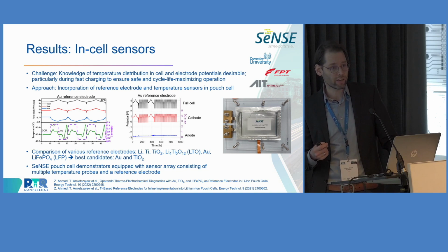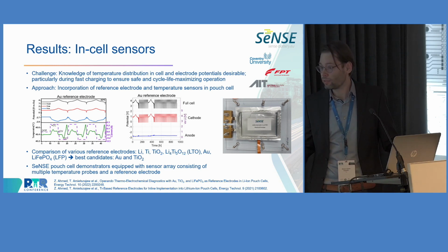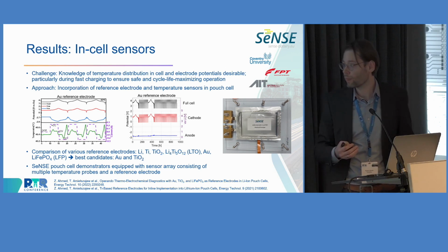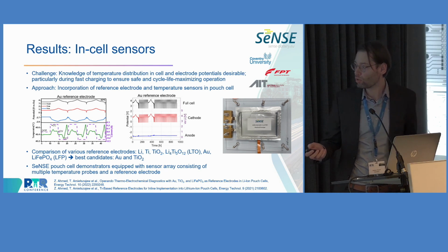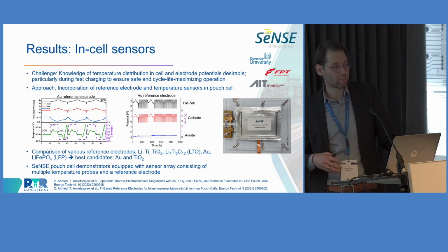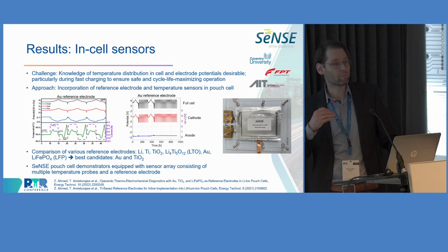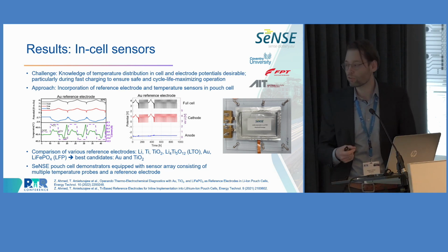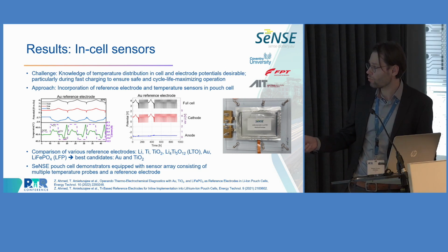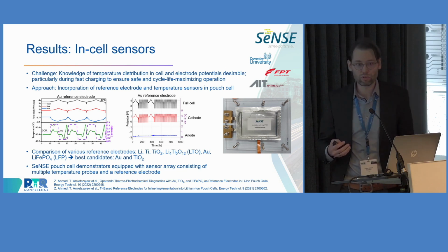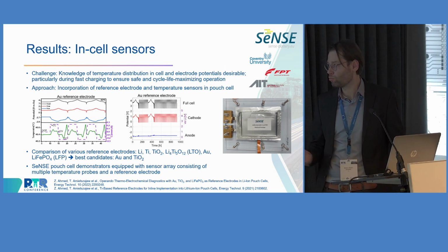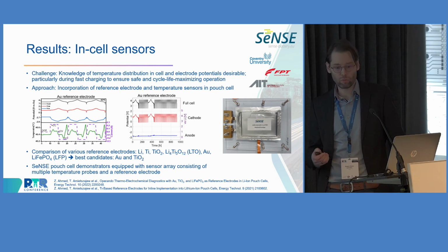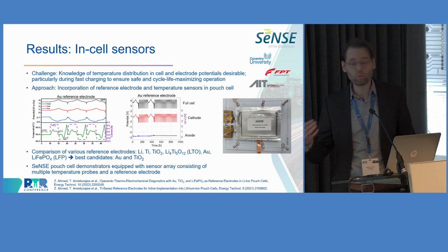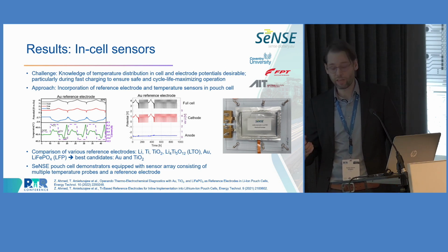And if you have a reference electrode inside, you can really monitor the electrode potentials individually for the anode and the cathode. And it turned out that both gold and titanium dioxide are quite promising candidates, because these reference electrode materials offer long-term stability in the cell and also don't require a pre-lithiation step that is needed for some other reference electrode materials. And as I mentioned before, the first pouch cell demonstrator that we produced last year incorporates temperature probes and also a titanium dioxide based reference electrode. And at the moment, we are working on fast charging algorithms that make use of these sensor data.